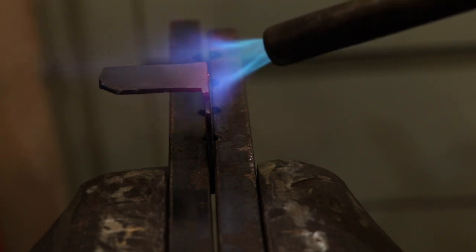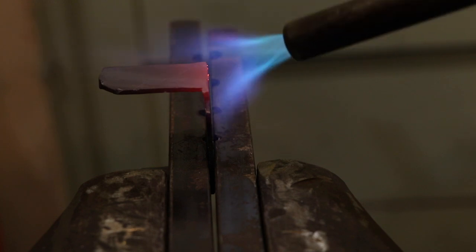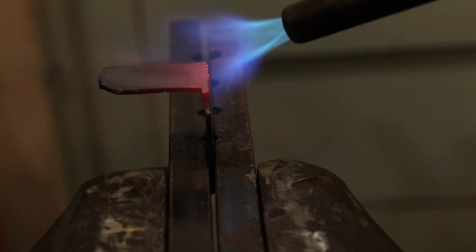It's really important to do that before you start to feel that the metal is resisting the hammer blows because that means the metal is starting to work harden. If you continue to hammer you're going to continue to add stress to that metal to a point where the corner will actually crack.